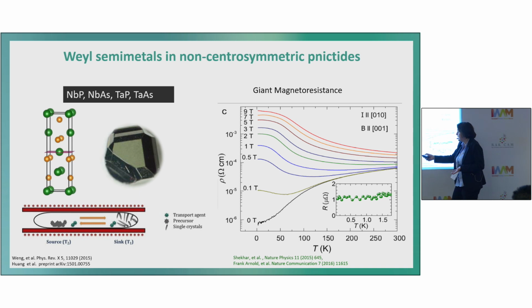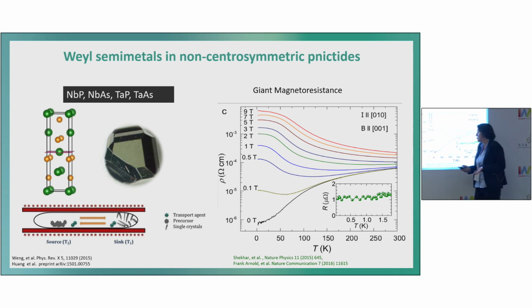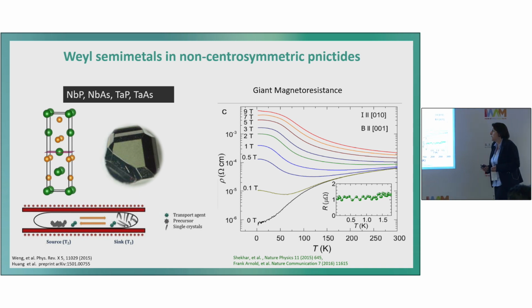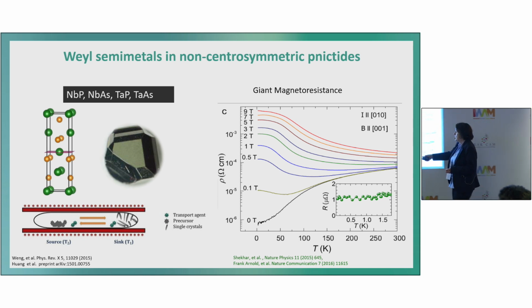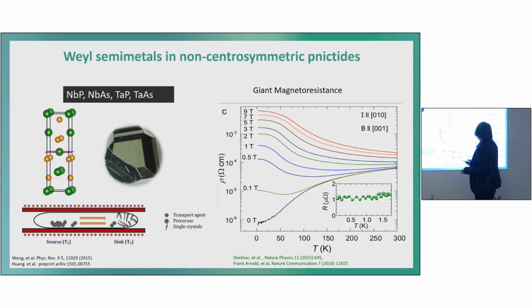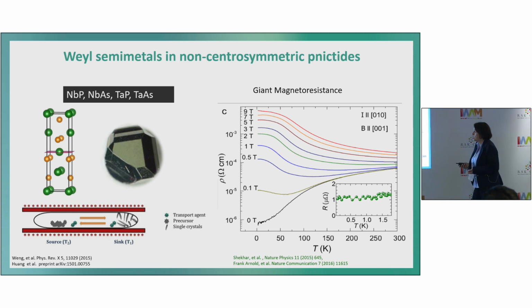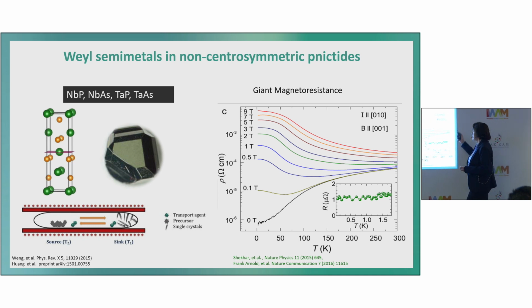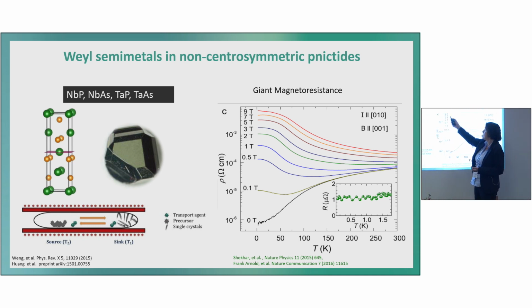You see some wiggles here, but these are not noise. These are nice quantum oscillations. So we know exactly the band structure of these materials because we can transfer these wiggles into the band structure. But if we apply a magnetic field, we can strongly increase the resistance in this material. Then at, for example, 9 Tesla, we have a kind of plateau, which we know from the topological insulator, which means it's insulating in the bulk and probably has some metallic surface state.